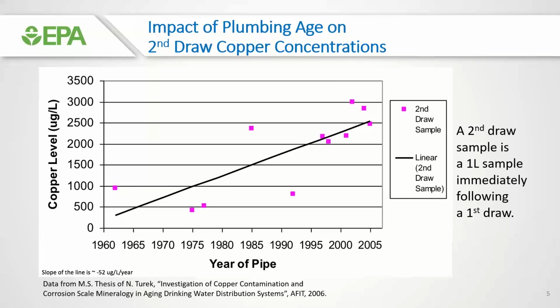And why is this important from a practical standpoint? Well, again, when we think about the Lead and Copper Rule, we're targeting worst case lead sites. That would be locations that have lead service lines, and of course, those are going to be older facilities. So to catch a high copper level associated with a lead service line site might be a bit tricky. It would have to be some sort of situation, perhaps, where there'd be a replumb or something like that. But generally, the two don't go together. That's kind of the point of this.